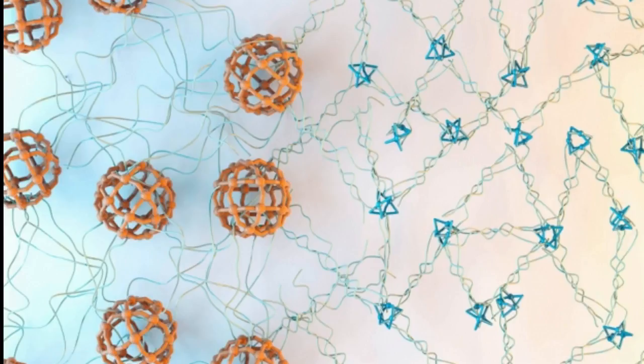The size of the cages is determined by the angle of bonds that a nitrogen molecule on the ligand forms with palladium. When DTE is exposed to ultraviolet light, it forms a ring in the ligand, which increases the size of the angle at which nitrogen can bond to palladium. This makes the clusters break apart and form larger clusters.